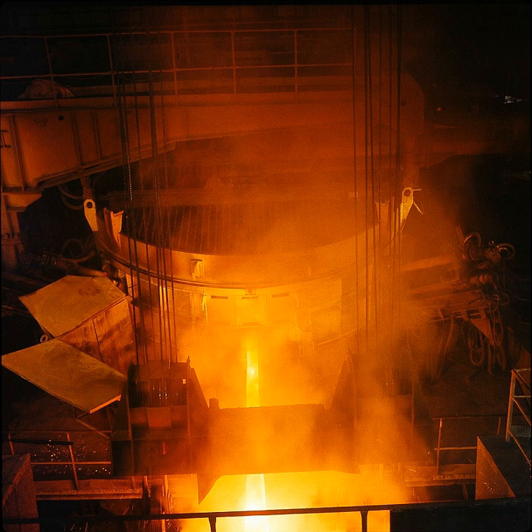For a furnace with basic refractories, which includes most carbon steel producing furnaces, the usual slag formers are calcium oxide (CaO) in the form of burnt lime and magnesium oxide (MgO) in the form of dolomite and magnesite. These slag formers are either charged with the scrap, or blown into the furnace during meltdown. Another major component of EAF slag is iron oxide from steel combusting with the injected oxygen.